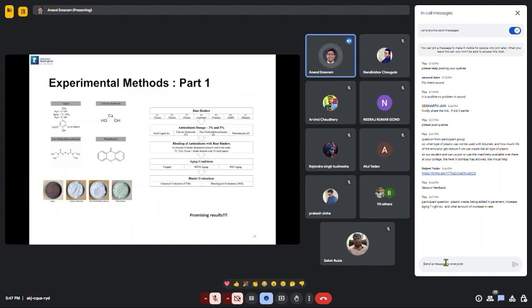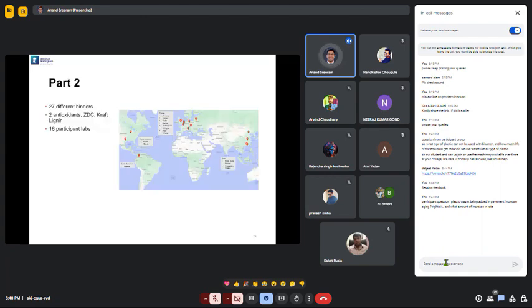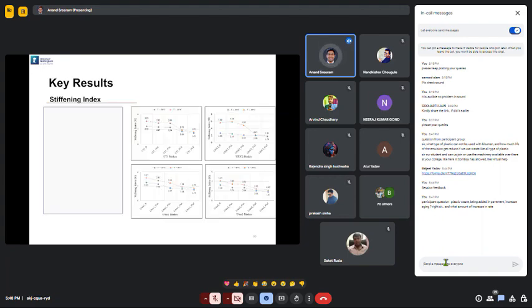In the first phase of the consortium, we looked at 4 specific additives, things like lignin, calcium hydroxide, zinc, phenothiazine, and then we conducted round robin laboratory testing, and we were able to see promising results. And in part 2 of the consortium, we had about 27 different bitumens and 2 antioxidants that we looked at, zinc as well as kraft lignin, and about 16 different labs around the world participated in this effort.